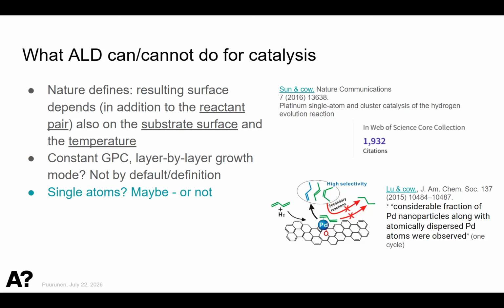Okay, single atoms. So this is where I hear that many people are interested in ALD at the moment, and in favorable cases, ALD can of course be a really good method for making those, but it is possible, depending on the conditions, that already after one cycle you actually have clusters. And here I have cited, among the much cited early single atom catalyst works from ALD, one from Junling Lu, where they already noted that in addition to these atomically dispersed palladium atoms, there were already palladium nanoparticles present. So there's promise, but you need to check.